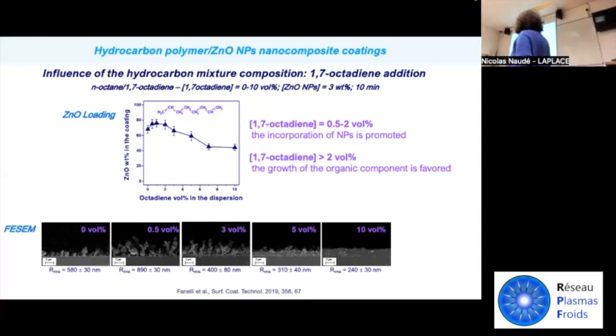And as you can see, if you look at the zinc oxide loading, at least in our process, we observed that when the concentration of octadiene is really low, lower than 2% by volume, it seems that this promotes the immobilization of nanoparticle agglomerates in the coating. While if we further increase the concentration of octadiene, we can really observe a decrease of the zinc oxide loading. And as you can appreciate from the SEM image on the left,